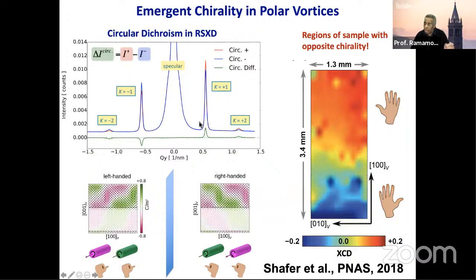Now, with all the synchrotron capabilities, not only can you do diffraction with soft X-rays, you can also do spectromicroscopy with that. Meaning, I can come in with right polarized and left polarized light, and I can do an absorption spectroscopy experiment sitting at this Q value at a particular point in the diffraction space, in Q space. And if you look at it very carefully, there is a measurable difference between the blue and the red, what the X-ray folks will call circular dichroism. And therefore, this array of vortices shows circular dichroism, which is antisymmetric, meaning the plus Q and minus Q are of opposite sign.